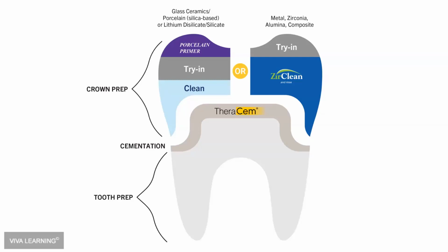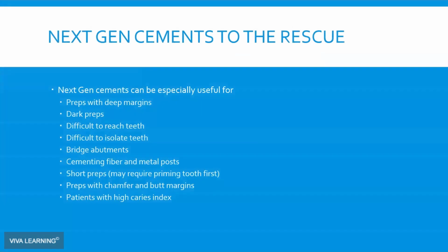Then you can put the Theracem. For metals, zirconia, and composites, you can also silanate composites, but it's somewhat optional depending on what you're trying to achieve. But after trying in, you can do the zirconia cleaning agent before the Theracem, or you can do the method which I do, pre-prime the crown with an MDP-containing zirconia primer, then do the try-in, then you rinse, and then you deliver with a next-gen resin cement.